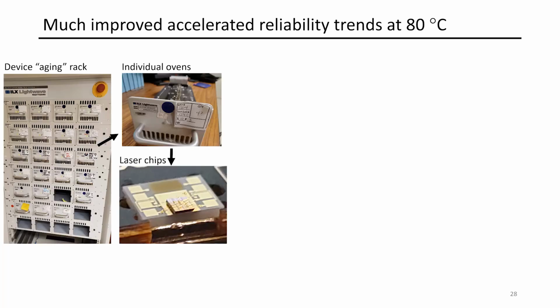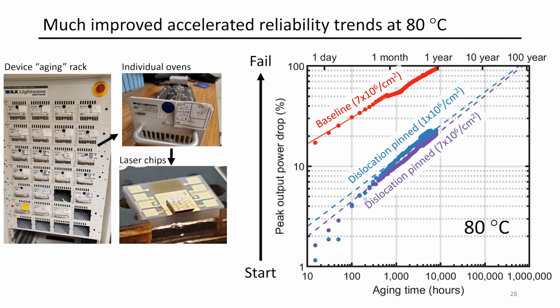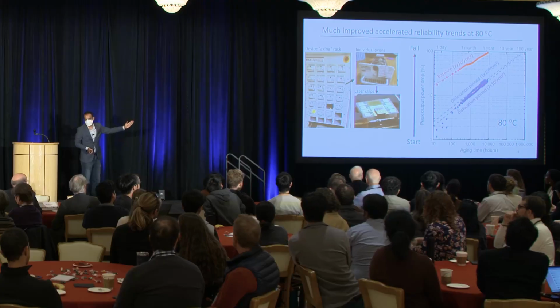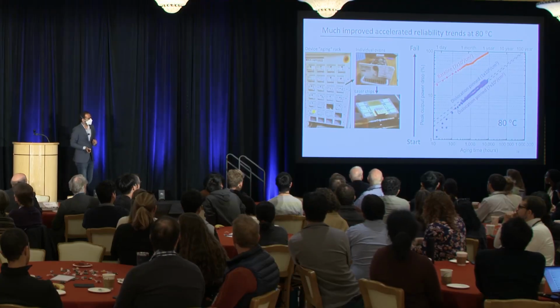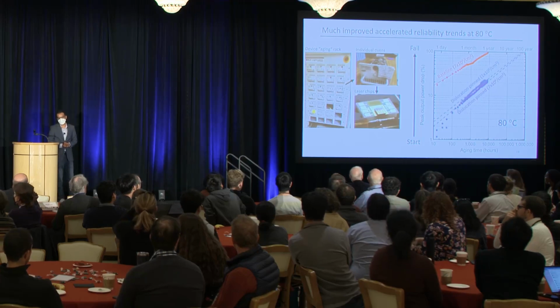So we now do these experiments where we take these little lasers, put them in these little oven-sized, like cookie heating ovens, right? And then we run them for a long time. In 2020, the record was the red line, where lasers were lasting about a year before they die at 80 Celsius. Which nobody in industry gets excited about because if they die in a year, you will never buy it. You need to have them last decades. That's how reliable these need to be. And just by using the dislocation pinning method, we've significantly improved the reliability of these devices. So these today are the record directly grown III-V lasers on silicon, surpassing tens of years of reliability.